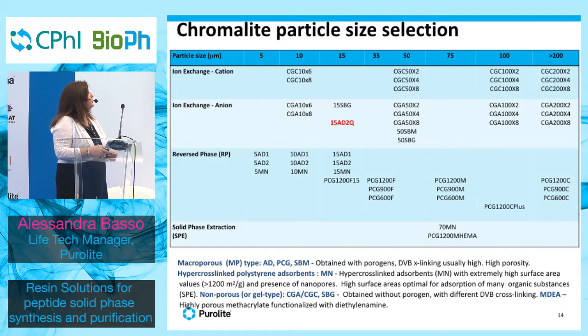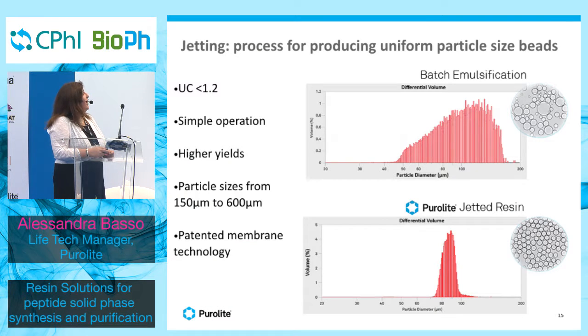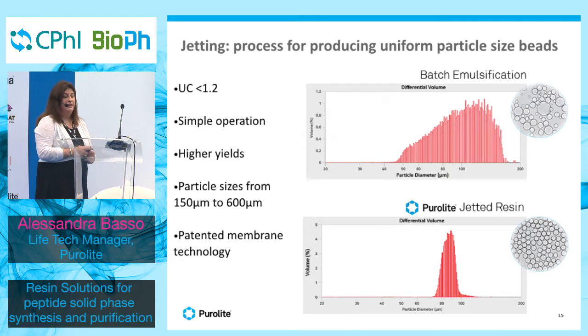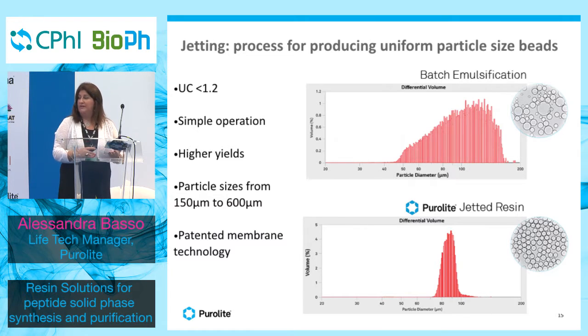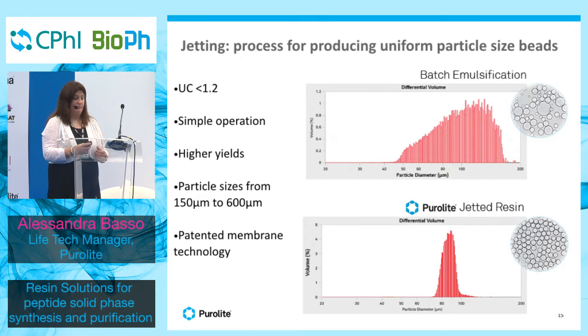We provide all these products in columns also, I will show you now. How do we make these products? Usually resins are made in a Gaussian mode. You see the batch emulsification, so you get the Gaussian, and then you have to screen to create the particle size that you need. Purolite has developed a nice way to produce resins that are jetted, as you see in the second picture. This method allows us to create very uniform particles, you see the picture of how they look. This gives us an economic advantage because we can provide resins at a very competitive price, and a very nice advantage in the application because the narrower the particle size, the better the separation, and the better the performance in purity and separation of the final peptide.